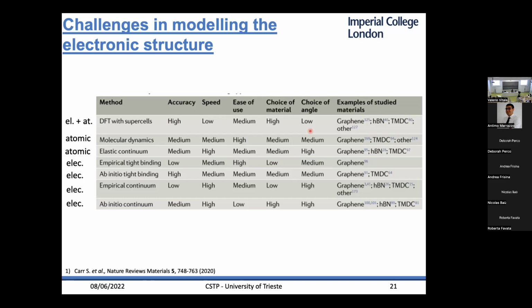So only large twist angle. For the atomic structure, you can use molecular dynamics and elastic continuum theory. These are moderately accurate, but are quite fast, particularly elastic continuum, although the accuracy is probably not as great. For the electronic structure, again, you would go with DFT, but there are other things you could do. In particular, these involve tight binding and continuum models.